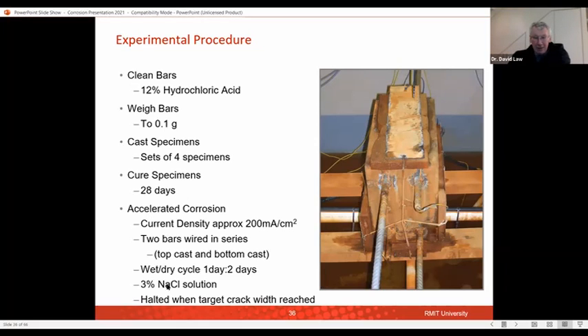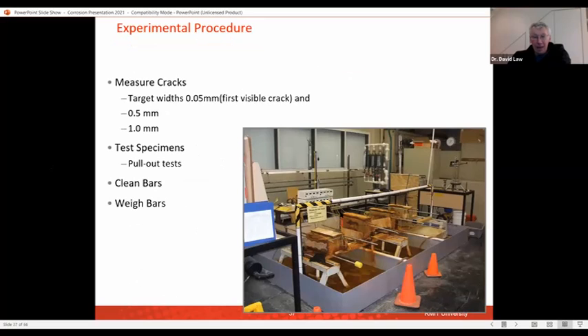pull them all out. In this case, we cast them with 3% sodium chloride, and we had wet dry cycles running for 1 day wet, 2 days dry, and we would stop these at specific crack widths to test what the bond was on them. Here you can see sort of the specimens again in a spray cabinet that we were looking at for them.